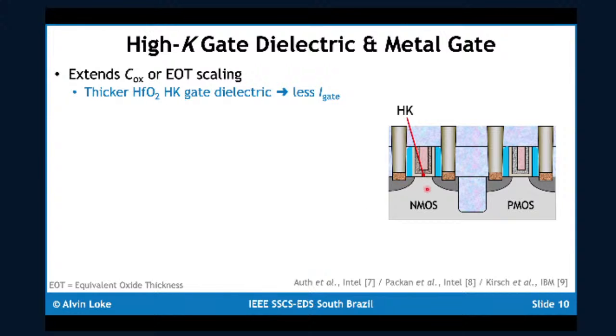By making the hafnium dielectric thicker, and because of its higher dielectric constant, you can still preserve your COX. That thicker dielectric is effective at suppressing gate leakage.